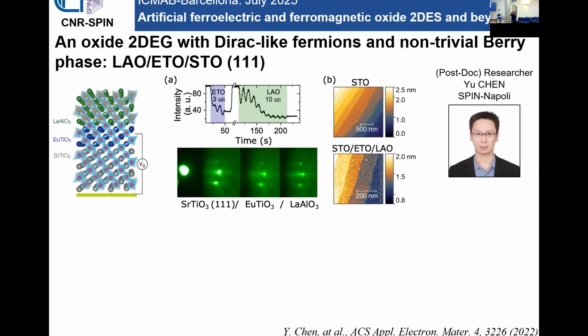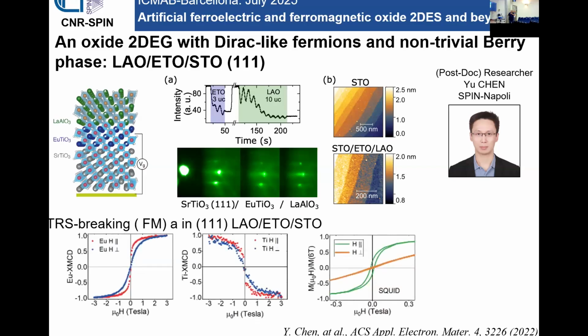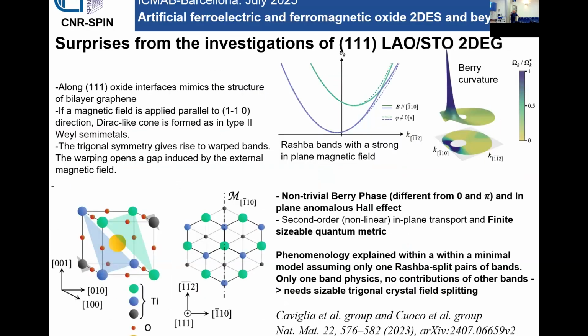The material grows in a decent way. We can grow nice heterostructures, and also show ferromagnetism at both the europium edge and the titanium edge, again with in-plane easy axis. Here the hysteresis is not very clear, so we performed a SQUID measurement to have a clear signature of the hysteresis in the magnetization. And so the system more or less shows time reversal symmetry breaking and spin polarization, like in the LaAlO3/STO system.